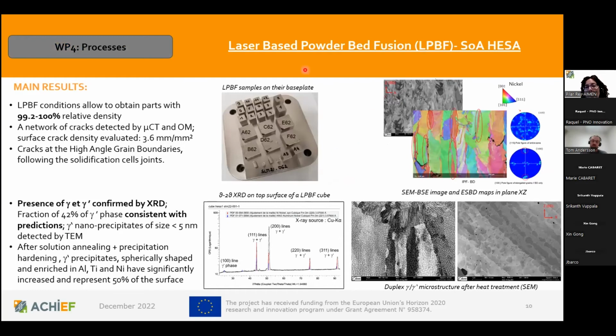When we move to the PBF process with the first material, we get relatively good bulk density, but the problem is that we get a network of small cracks that we detect using tomography and optical microscope. These cracks are situated at the high angle grain boundaries, following the joints of the solidification cells. So the quality is not as good as we expected at the beginning. In any case, we went further in the analysis and detected the presence of the gamma prime phase, which was confirmed by XRD analysis. After some thermal treatment, this gamma prime increased and reached almost 50% of the composition.